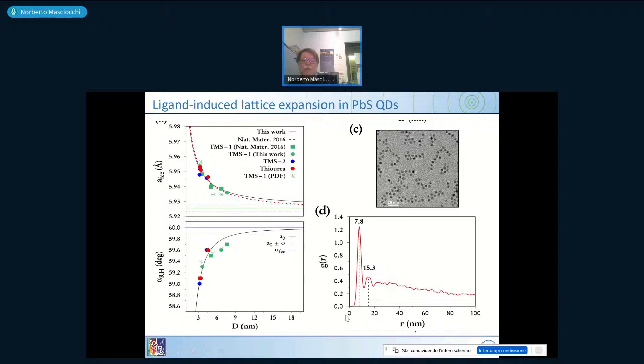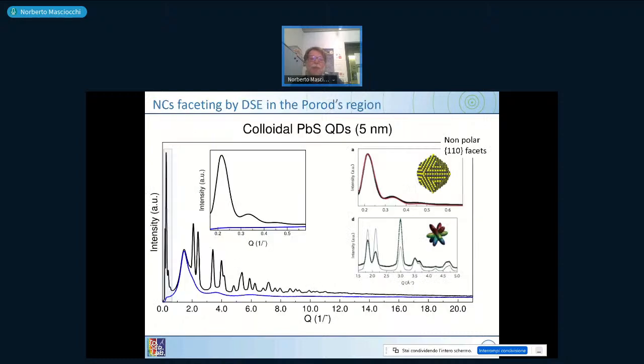So at some distances, you have a large peak. At 7.8 distance, you have a presence of many dots. Twice as much, you have another one, and possibly a third one here. So this is a g(r), which tells you that particles are not randomly distributed, but try to align. 7.8 is nothing else than the 7.7 size of the dots we've seen before. We have measured before nearly 7 nanometer size dots, and this is exactly what you observe with TEM.